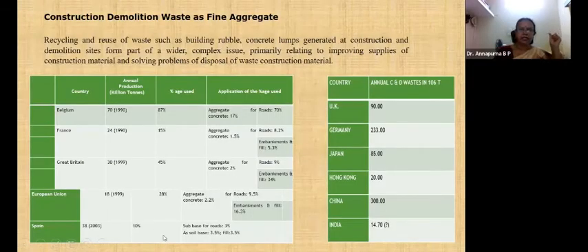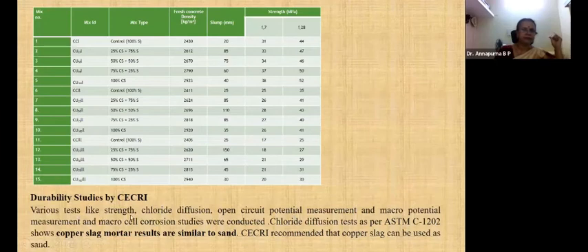Next is copper slag here. Durability tests they have done on the copper slag and seen that the chloride diffusion test as per ASTM C1202 shows copper slag mortar results are similar to sand. So this can be recommended for use as sand.